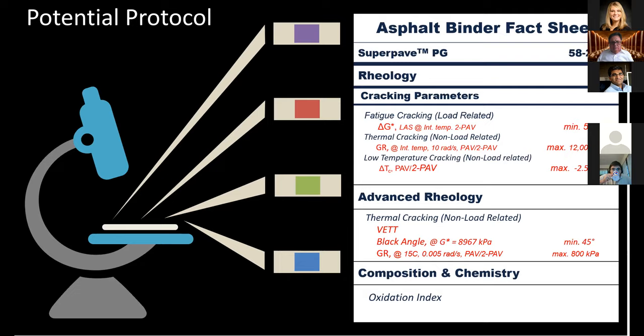They were proposed by the researcher based on the results thus far of this study, and you could see in the graphs. So we would be looking potentially at cracking parameters of delta G for the fatigue cracking, the thermal cracking, we would look at Glover-Rowe, and then low temperature cracking, we would look at delta Tc. For kind of the advanced rheological look, that thermal cracking, we might look at the black angle and the Glover-Rowe at the different temperatures. And then we're not sure exactly how we intend to look at the oxidation indices, but we would like to use those as a determination of percent change or a maximum change perhaps, or some criteria that we would look at those.